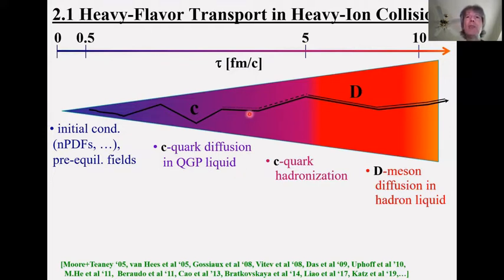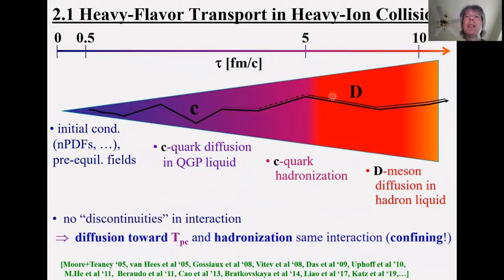Now, one point I want to make here is due to the fact that, as I showed on the previous slide, the transition in QCD, at least at zero chemical potential, on the temperature axis, is a crossover. We should also expect that there's a continuity in the interactions that the charm quark undergoes. So in other words, the interactions which ultimately hadronize the charm quark should be gradually building up as it approaches the transition temperature. And as such, it is very suggestive that the confining interaction that color neutralizes the quarks should already play a role before the hadronization occurs, already in the Quark Gluon Plasma. So there is no discontinuity in interactions, and hadronization and diffusion, at least at not too high temperatures in the QGP, should be related. Of course, the suggestive candidate for that is the confining interaction that may have remnants in the QGP.